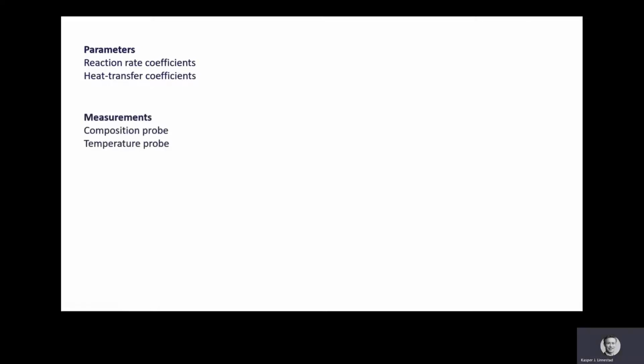In order to get the model to represent the plant in the best possible way, we have carried out a parameter estimation campaign to fit the model to the plant data. Main parameters we have estimated are the reaction rate coefficient and the heat transfer coefficients. The measurements we have used are the temperature and composition probes that are taken at the end of each batch. We have used 1 month of online data containing around 850 batches. The parameters were estimated by minimizing the sum of squares of the measurement error.